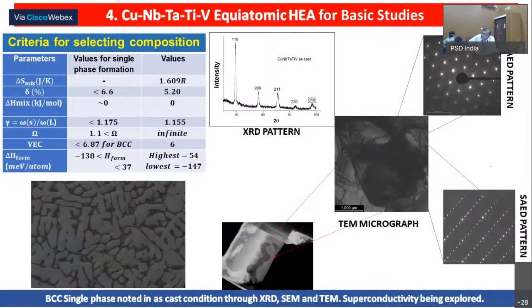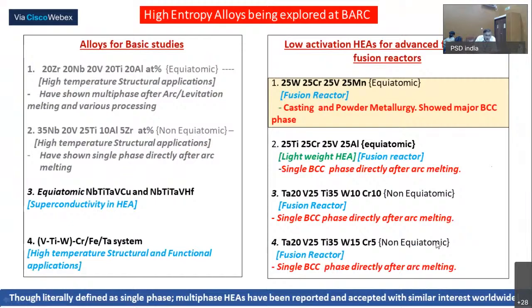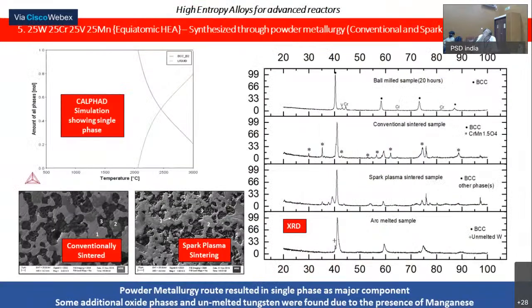Now, once we got excited about this, we started working on another alloy system. Why not look for a material which can have an even higher tendency for superconductivity? So we explored another material where we started adding copper. The moment you add copper, you are actually deviating from the high entropy alloy concepts, and what you end up with is the formation of a single phase again, but the composition is different. But in between, very faint, these are very small FIB lift outs, nearly 10 nanometer lift out, and you see these small patches, they show a phase which is showing some ordered structure.